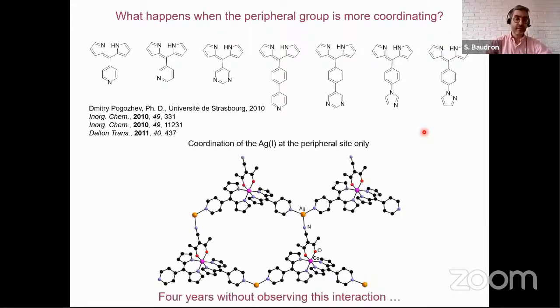But surprisingly to us, in this case, we had what we had anticipated at the onset of our study, only the coordination of a peripheral group to the silver(I) cation and no silver-pi interaction. So we went on for 4 years without observing this interaction with this set of ligands. And we wondered at the time whether it was because those ligands were more strongly coordinating than the nitrile, and the silver had a complete coordination sphere in this case.